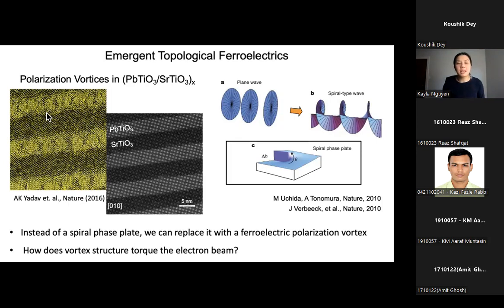So now what we can do is take a plane wave of electrons, basically a regular electron beam, and scatter it off of one of these lead titanate, strontium titanate polarization materials and see what we get. In general, instead of a spiral phase plate, we can replace it with a ferroelectric polarization vortex. What we want to know is how does this vortex structure torque the electron beam? For example, if we want to use it for real devices, how are we going to utilize this polarization mechanism in a real device? One way to do it is to characterize that with the electron beam.